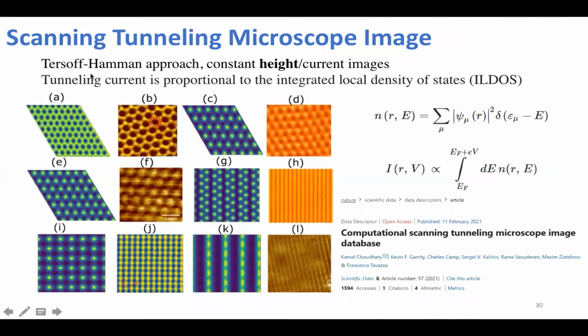So we use the STM Tersoff-Hamann approach with constant height and constant current images. The Tersoff-Hamann approach is based on the idea that tunneling current is proportional to the ILDOS, or integrated local density of states, which can be computed using density functional theory. Here's an example for 2D materials, which are especially suitable because they don't have many dangling bonds. In the first and third columns we have the simulated images, and the second and fourth columns are the experimental images. You can see they compare really well for the STM images. This was published in the Nature Scientific Data journal.